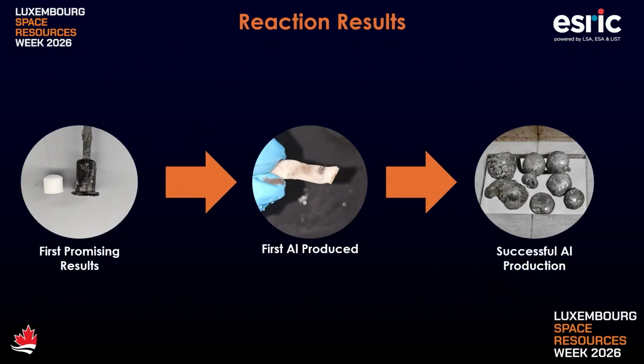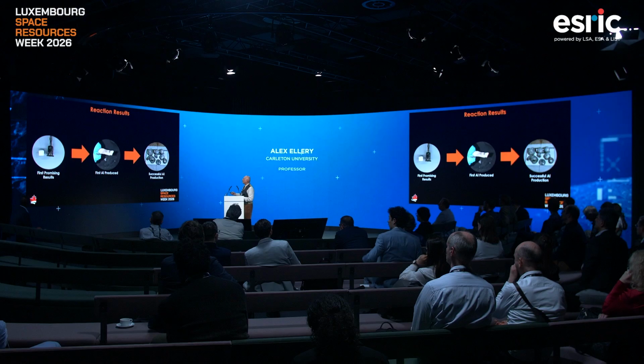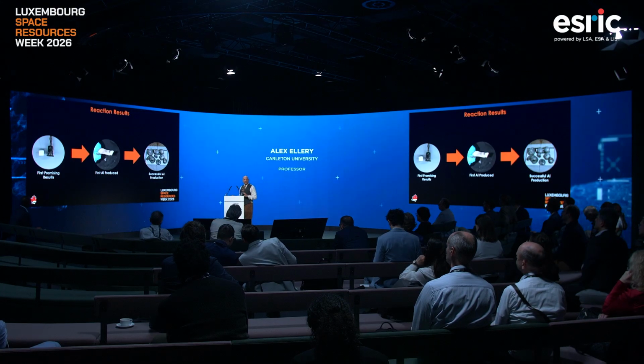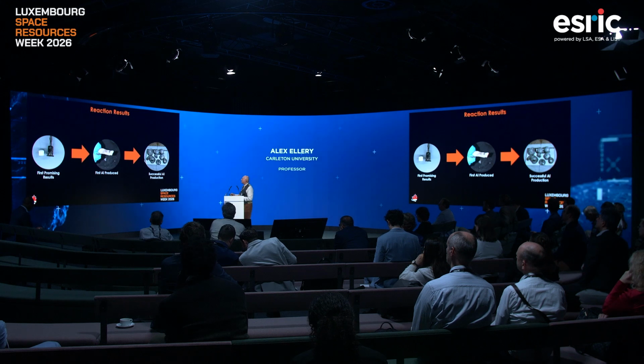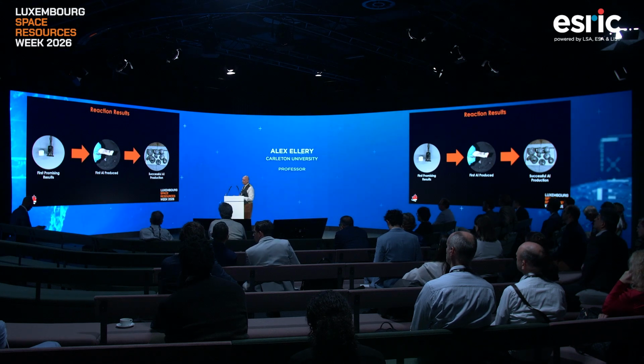This was the first attempt. It didn't look very nice. This is another attempt. This is actually some of the aluminium we ended up with. And then finally, this is what we actually ended up producing from the liquid. The liquid is tapped off because aluminium is molten at 900 degrees. And we managed to produce these aluminium pellets.